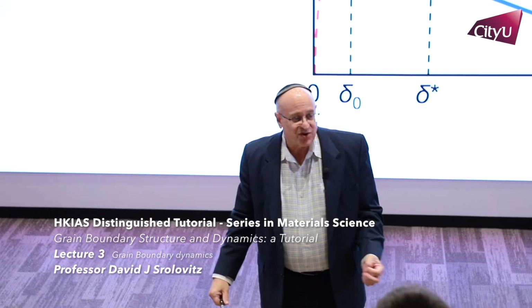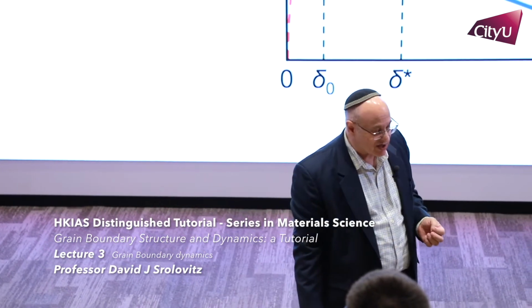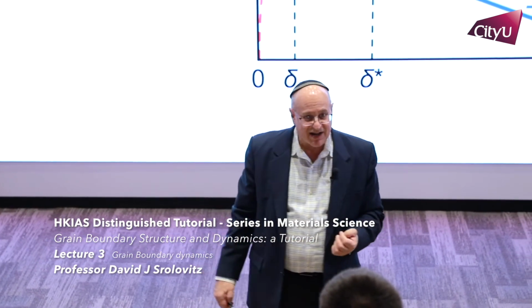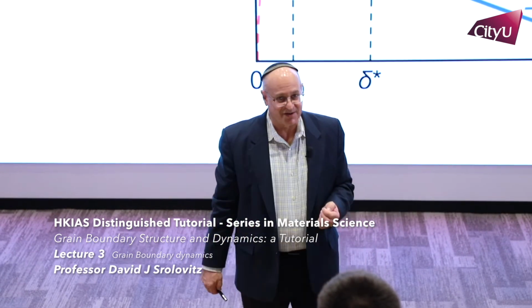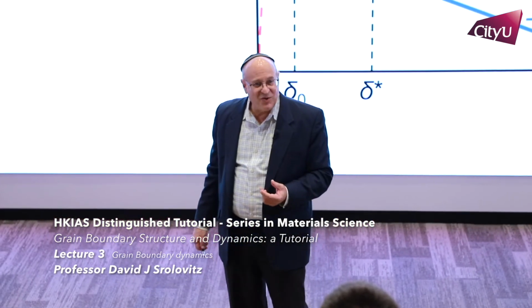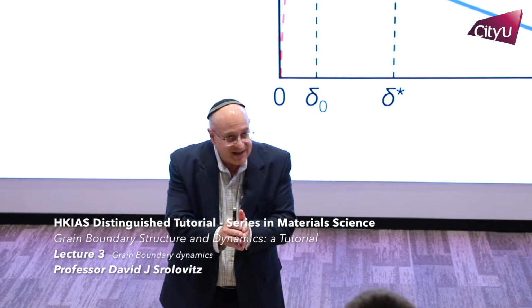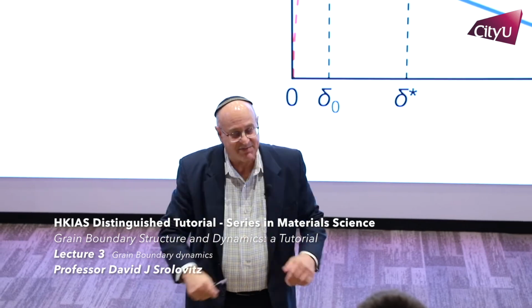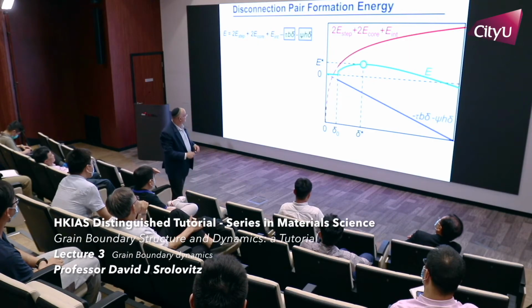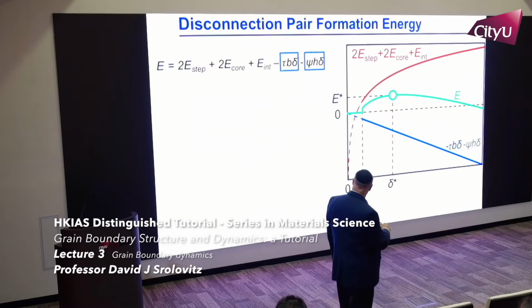You know, if I ask you the question, what is the equilibrium concentration of dislocations in the material? The answer is always 0. And it's 0 because however I put them in, they just want to collapse back, unless I apply a stress or I apply a chemical potential difference. So as I showed you before, the stress couples to the Burgers vector and couples to that delta.